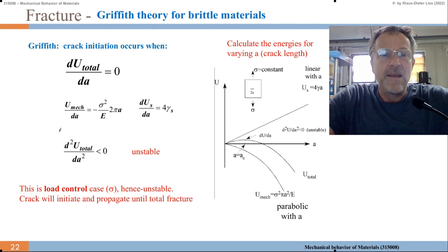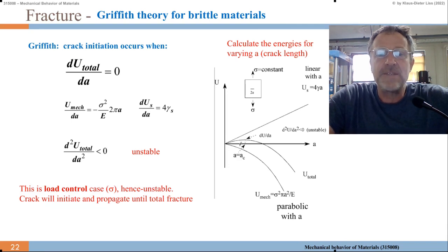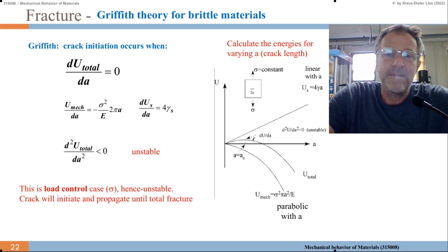Because the second derivative, the curvature here, is convex, d squared U total over dA squared is smaller than 0, and that means this is an unstable equilibrium. If we are at smaller A than A critical, the crack may close again. If we are at larger A than A critical, the crack grows.